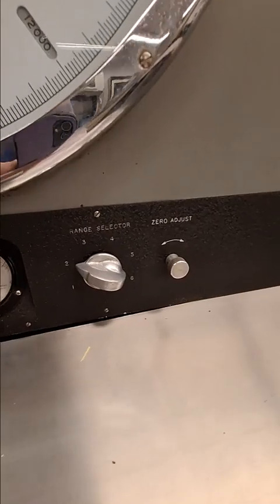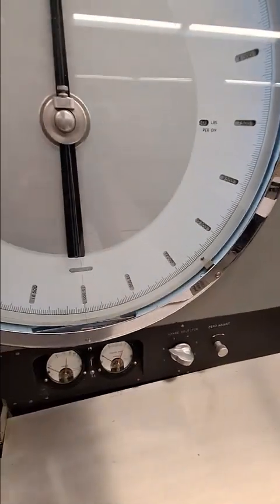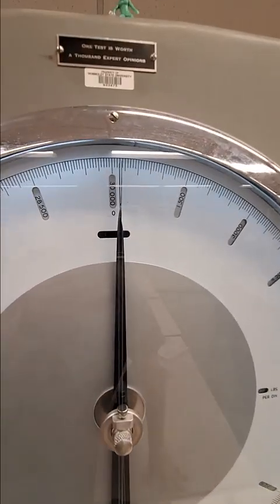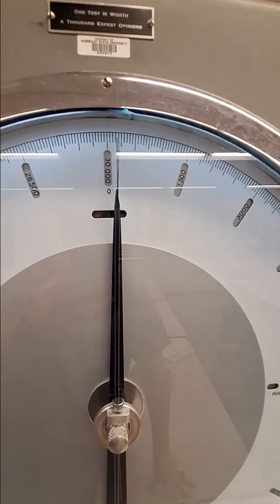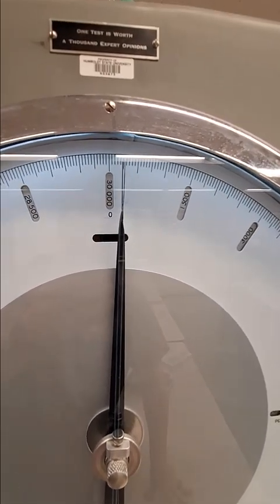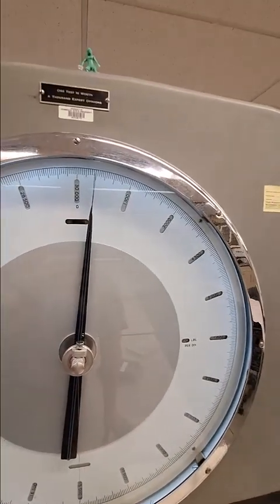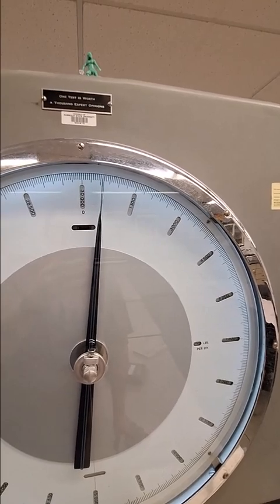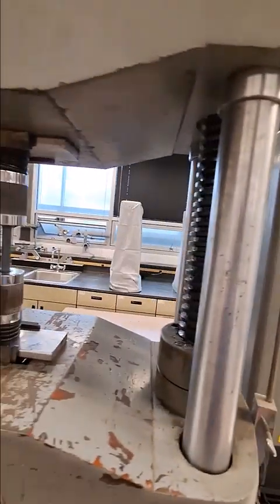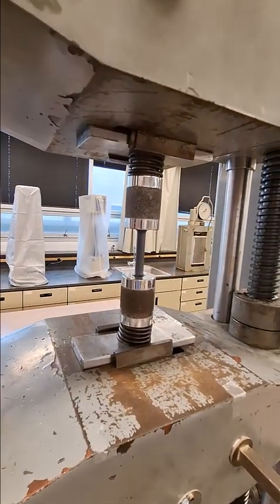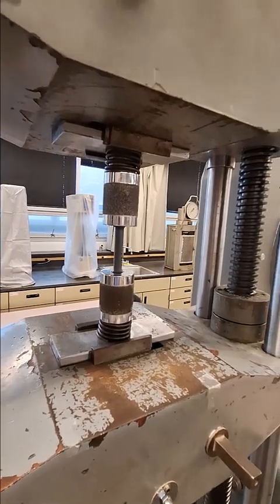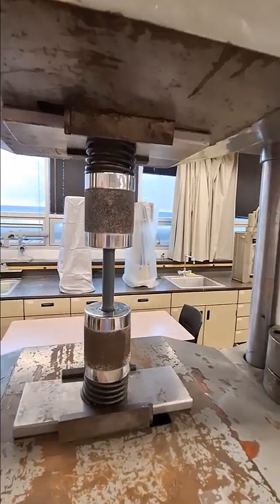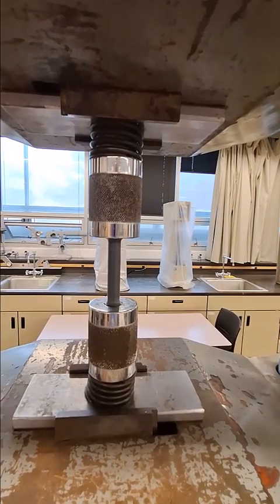We have a range selector for basically the amount of load that we anticipate. So we're at 30,000 pounds here. And now you can see that needle start to move. So we're actually loading our system. You see that the value is going to shift as we continue to increase the stress placed on our system. So again, we're moving 15 millimeters per minute apart, and we'll see how our system responds.